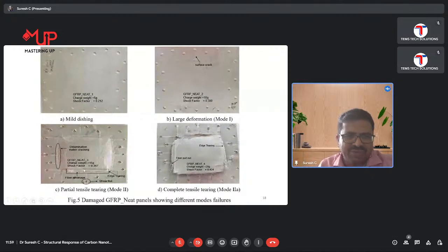And as I told, for 15 grams there was a delamination in the matrix of the composites and there was a tearing at one edge of it, and we measured the length of the tearing. That is what I was explaining previously. If you see for 20 grams, it was almost torn in all the edges and the complete center structure has been pulled out. So we are not able to measure the exact permanent deformation for 20 gram.